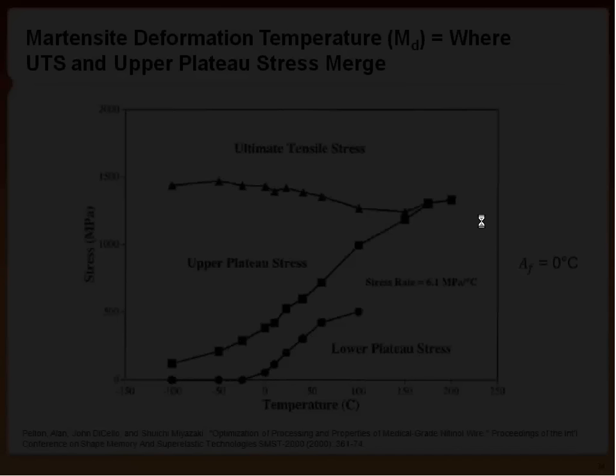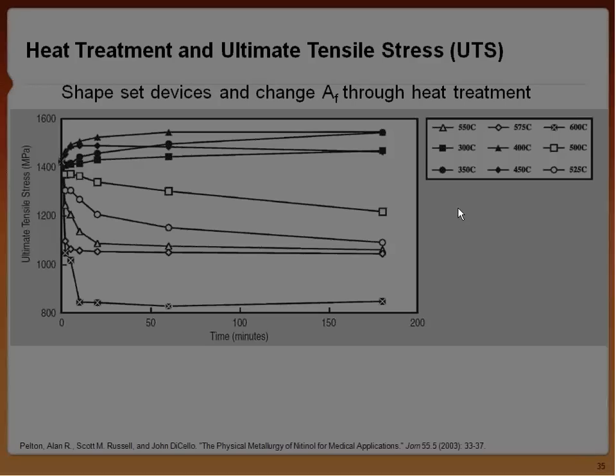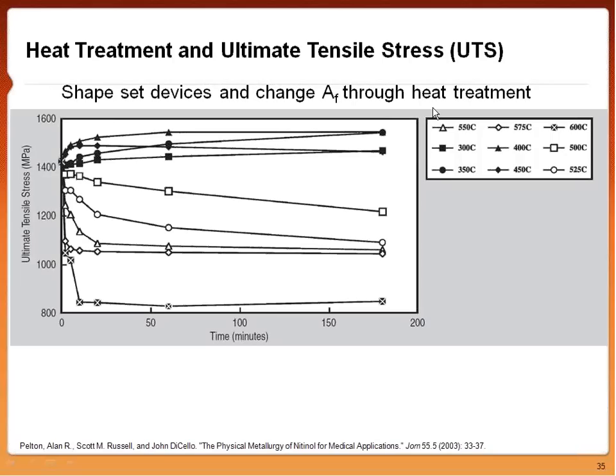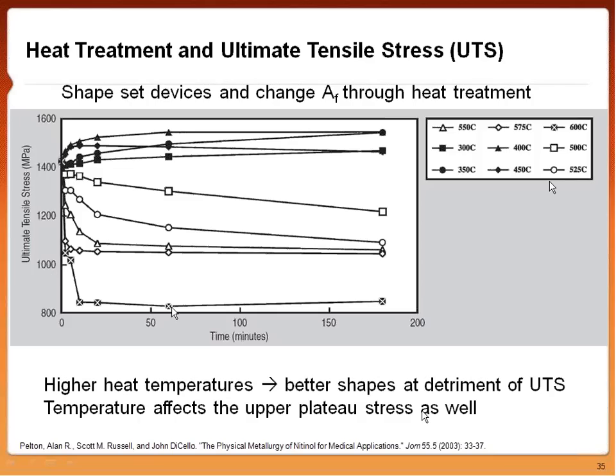So again, we want to change things to our advantage. We can heat treat or shape set our devices. So when we do that, we can get detrimental effects in our ultimate tensile strength of our material. It's basically a trade-off. So higher temperatures will give you a better shape. However, the better shape will have a detriment in the ultimate tensile strength of the material. So at 600 degrees Celsius shape set time is going to give you a good shape. However, the more time you do it, it's going to seriously decrease the ultimate tensile strength of your material.